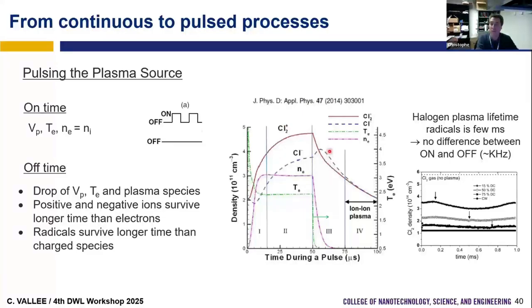And if we have less ion flux, we can also modify the DC self-bias, and we can modify the ion energy. We can also modify the ion energy by pulsing the substrate. So we can have a radical versus ion flux that is modified between the on and the off, and an ion energy that can be modified between the on and the off.